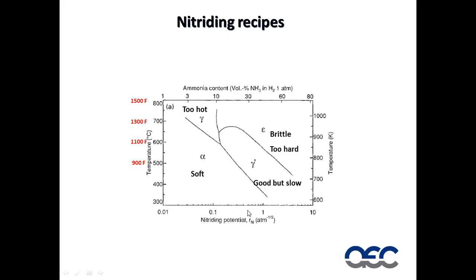So as we turn up the nitriding potential, we now move into a range here, which is this gamma prime. This is what we want. If we make gamma prime down here with high nitriding potential but at low temperatures, we will make a great nitriding layer, but it will take us until next month to achieve it. So we need to go hotter to speed things up. If we, however, go too hot, we go into this epsilon range. This is the white layer. This is the brittle layer we do not want to create.